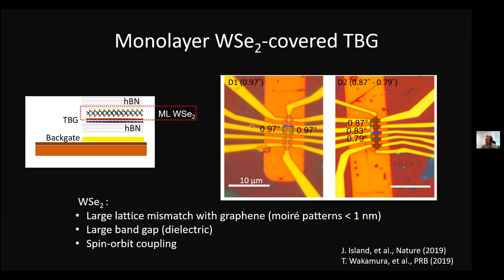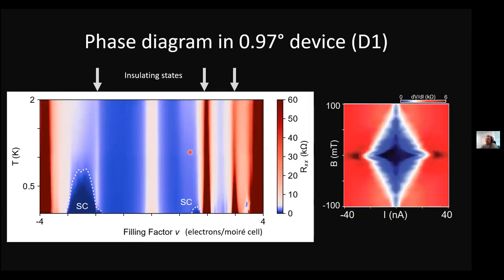So let's see what we see in these low angle devices. If you start with our highest angle device, you basically see all what you're supposed to see. You see the magic angle physics. This is your half filling state on the hole side. This is a correlated insulator on the electron side. This is 3/4. And you have this superconducting pocket on the hole side around -2 filling factor.